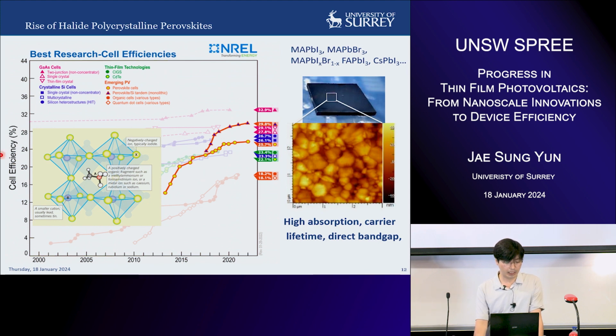So halide perovskite has an ABX3 crystal structure. At the A site, we have an organic cation, which is sitting in the middle here, and the B site is usually lead. It's hard to actually replace lead with other non-toxic materials. So there is always going to be lead in a high efficiency perovskite material. And this lead is surrounded by halide ions such as iodine or bromide, which form an octahedral structure.